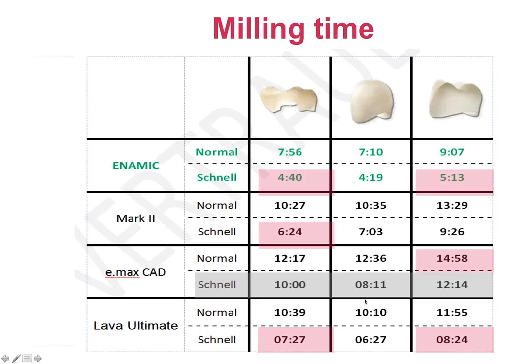Milling behavior. It's very fast, efficient. Now, you have to have the right software that has the right milling parameters for Enamic to get these times. If you don't have the new software with the Enamic in there, then you won't see these types of milling times. This was done by Sirona. So you see the milling times in the fast mode, Schnell, and the normal mode, normal. Then you compare it to other materials in this list. You see it's very fast, a crown, 5 minutes in the Schnell mode, compared to Lava Ultimate in the 8 minutes.